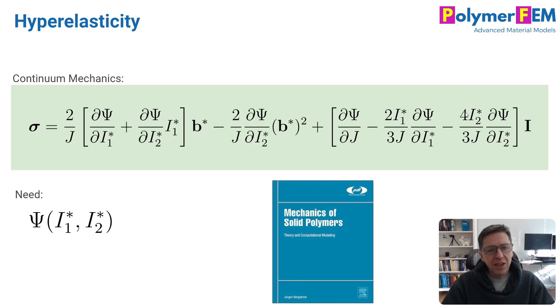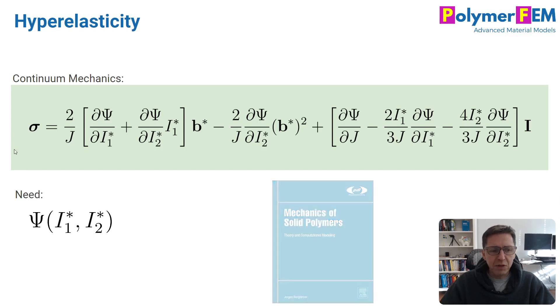If you read any text on continuum mechanics, including my book, you can find that the Cauchy stress in the material can be calculated from this equation if the material is hyperelastic. It looks like a very complicated equation with tensorial quantities, but really all the interesting stuff goes into the partial derivatives. This psi function is the stored energy and it depends on two invariants, i1 and i2.